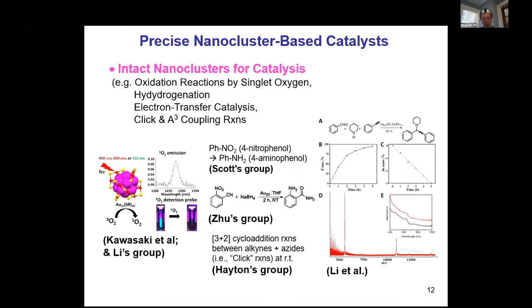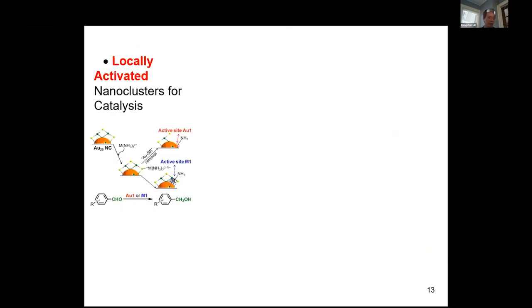So in this case, typically, if you want, you can use mass spectrometry and also UV to confirm whether the initial particle size or structure got changed, because the UV is sensitive to the structure and the size, and mass spec tells you the molecular weight of your nanoparticle, whether there's any change in size or reduction. So that's the most straightforward way you can utilize these well-defined nanoparticles. And typically, if you have ligands on a particle surface, the activity is usually more or less suppressed. So if you prefer to kick out one or a few ligands to increase the catalytic reactivity, that works.